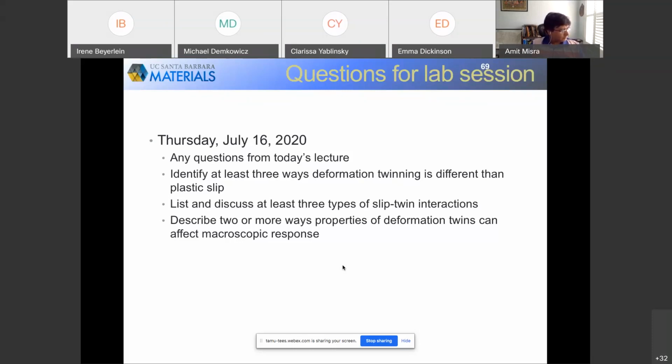So with higher strain rates, when you have smaller time scales, twinning becomes a more favorable mechanism, because it's easier and faster to move. The only cost is that it does require a high amount of stress, more so than slip. But when you have a high strain rate situation, typically you have the stress that you need. So I hope that answers the question.